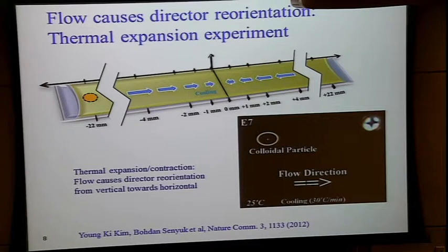So the anisotropy of viscosity and the presence of long-range orientational order lead to coupling between the two. As you have already seen from the expression for sigma, there are terms in which you have components of the director and the gradients of the velocity. So the result is that if you have flow in the system, that flow might realign the director. And the opposite is true: if you have realignment of the director, that creates flow. The second problem is a big problem for the display industry, but I would like just to illustrate the statement with